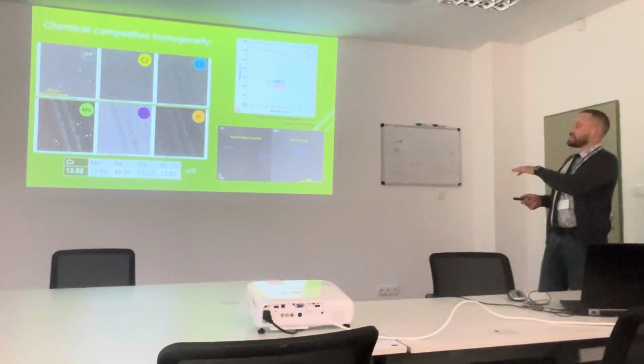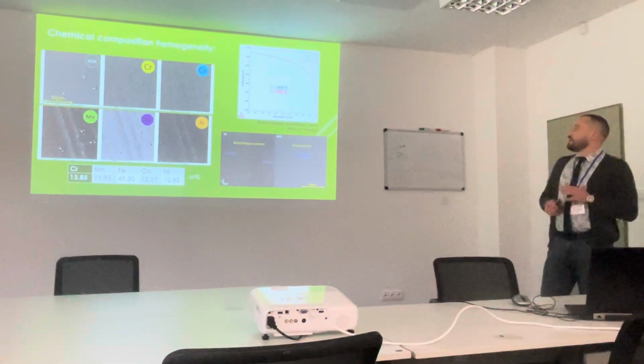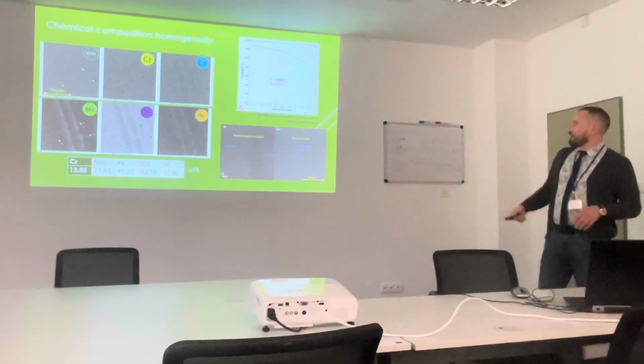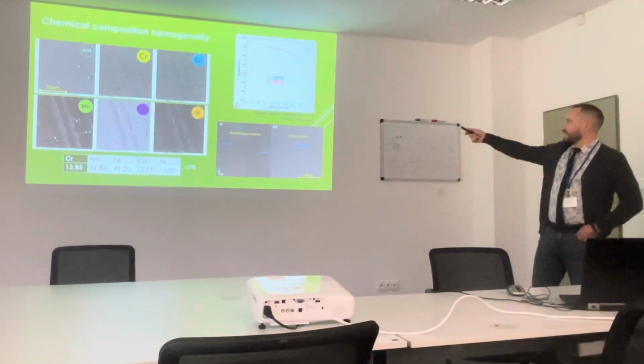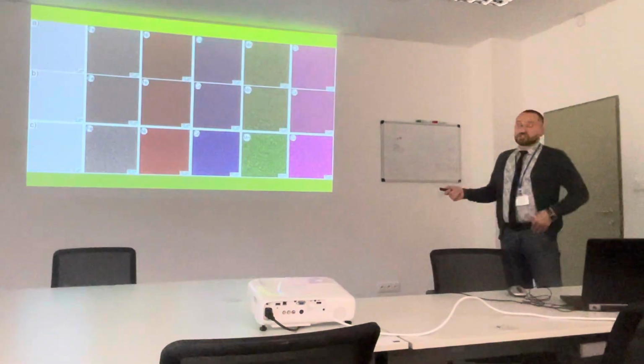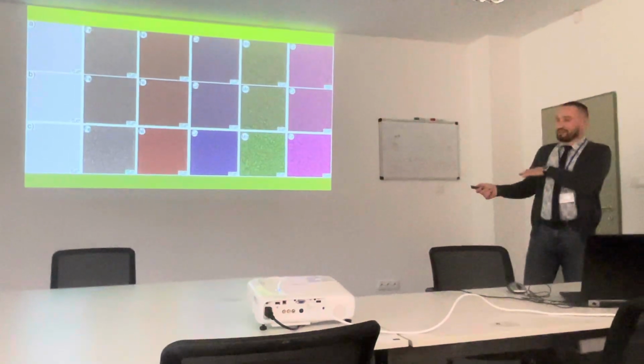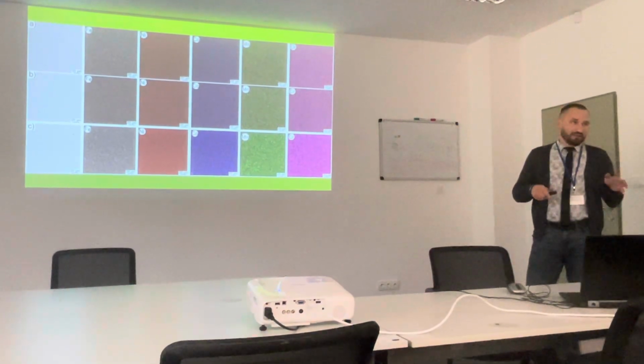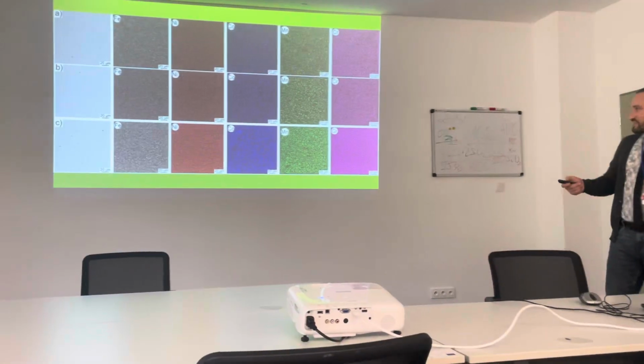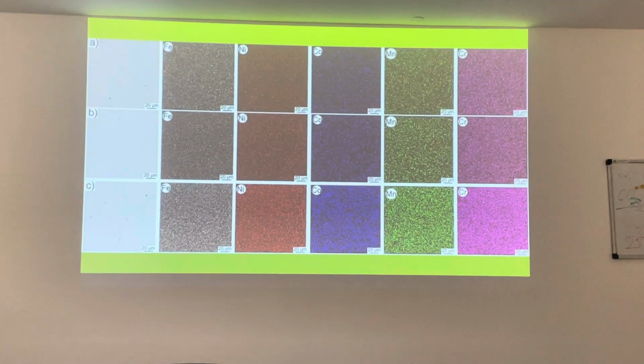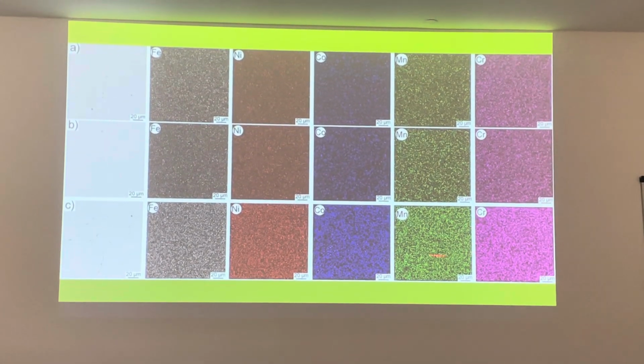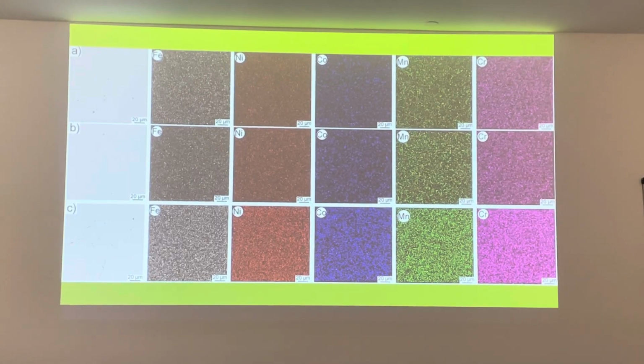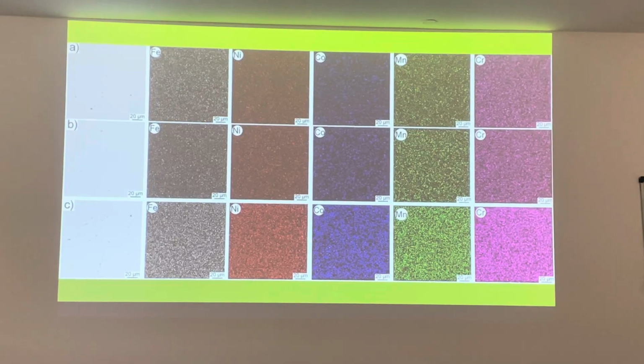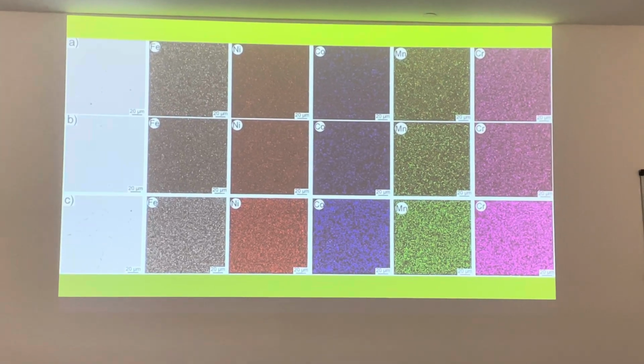Also, calculations were performed using Thermo-Calc with this chemical composition, and they show us that we have a single-phase FCC with a liquidus temperature of 1400 and solidus 1390 degrees Celsius. Also, we have made X-ray diffraction, and there were clear peaks for the FCC phase. So it's really an FCC phase. X-ray maps with scanning electron microscopy show the uniformity of distribution of elements from the bottom, middle, and top parts of the billet. So through the whole volume, we have uniform distribution of chemical elements.